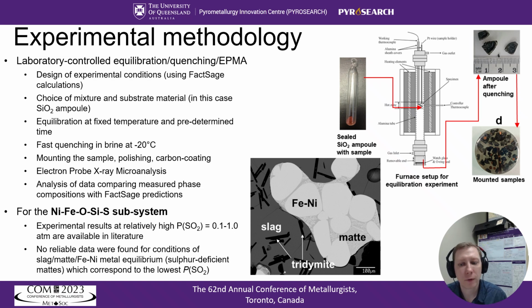The compositions of phases in equilibrium are measured by electron-probe microanalysis after the equilibration, so the experimental data produced is valuable even when small changes in bulk composition happen during the equilibration. In this case, we found that studies in the literature were focused on equilibrium at high partial pressure of SO2, but we were interested in conditions of equilibrium between slag, matte, and iron-nickel metal, which corresponds to low PSO2 and sulfur-deficient mattes.